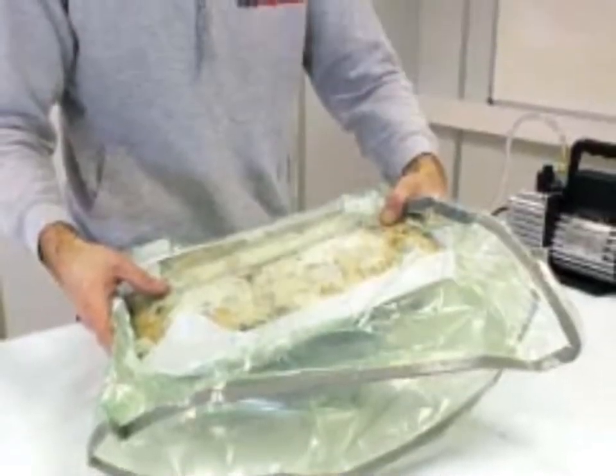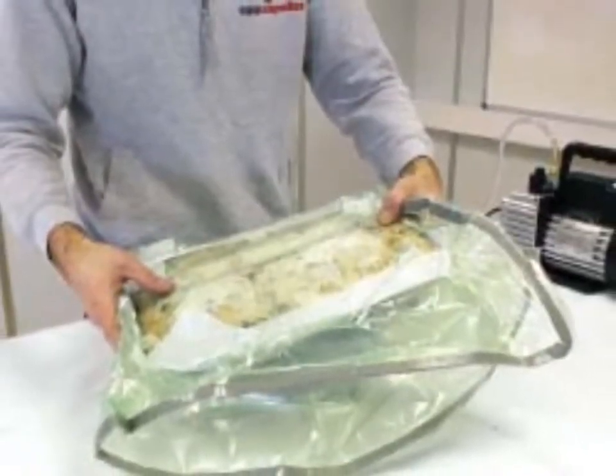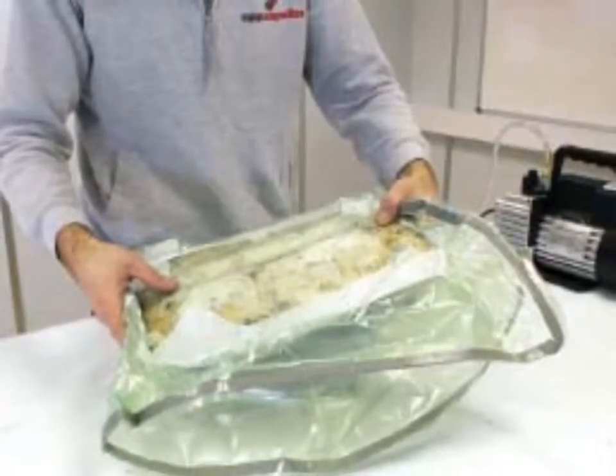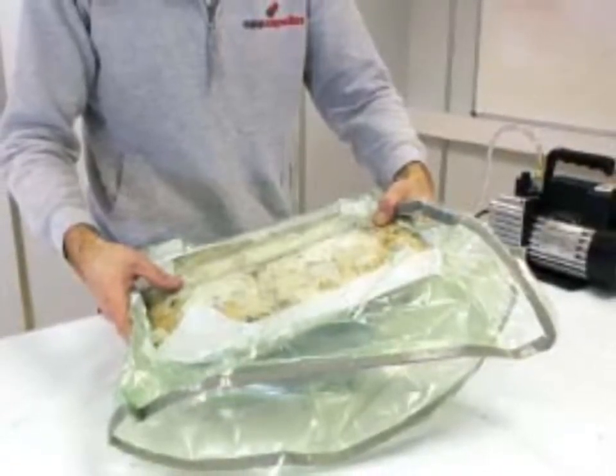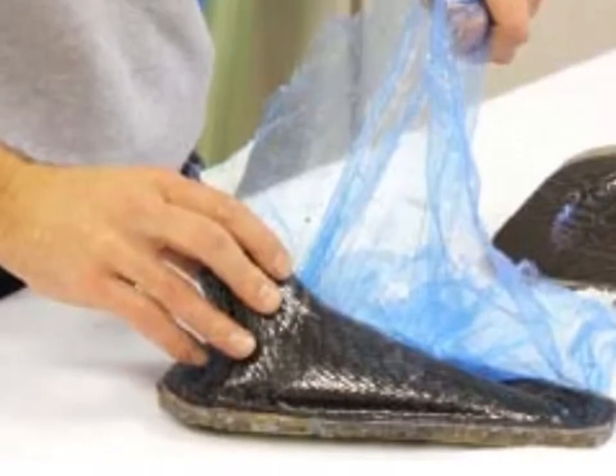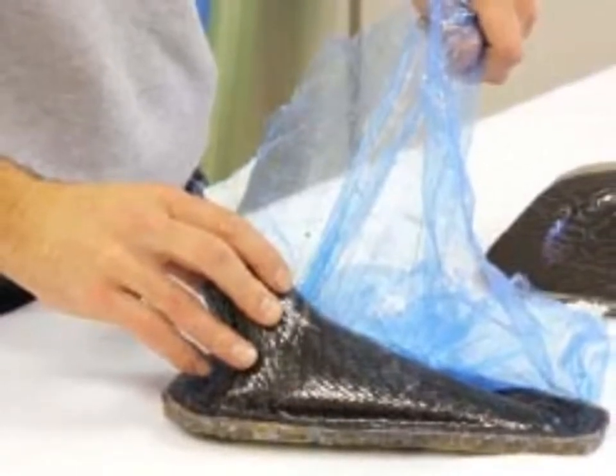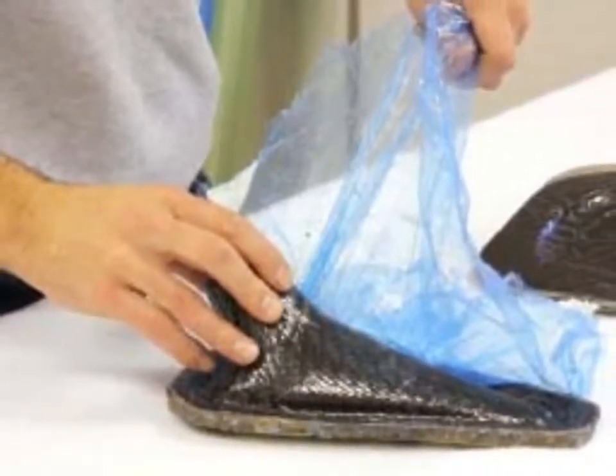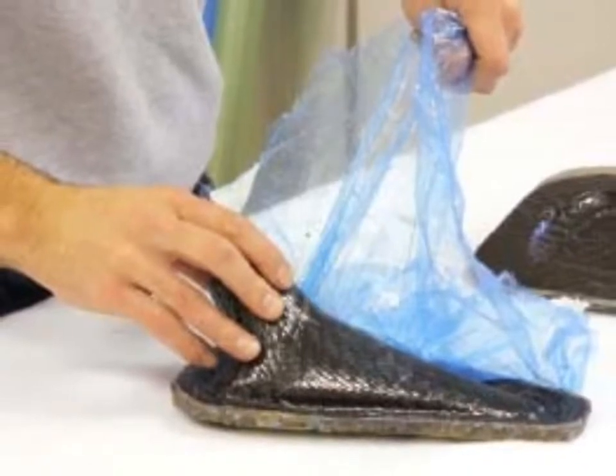The next step is placing the vacuum bag into the oven. The prepreg will be cured for about 8 hours. After curing, take out the molds and let them cool down for 1 to 2 hours. After cooling down, take off the release film off the parts and take the prepreg material off the mold.